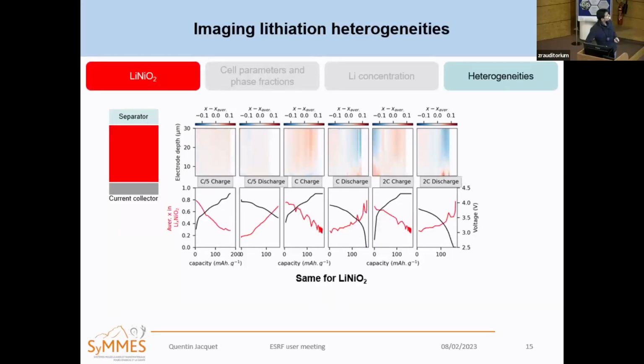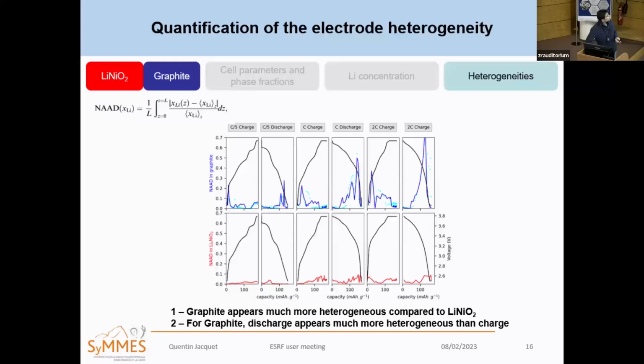For the LNO electrodes, the cathode, we basically see the same story. But if we look at quantifying the concentration gradient, we can do that by integrating this deviation to the average. And this is basically represented by this NAAD. Basically, the higher this value, the more heterogeneous your electrode is. And you can really easily see, comparing the graphite with the LNO, that graphite is much more heterogeneous than LNO.